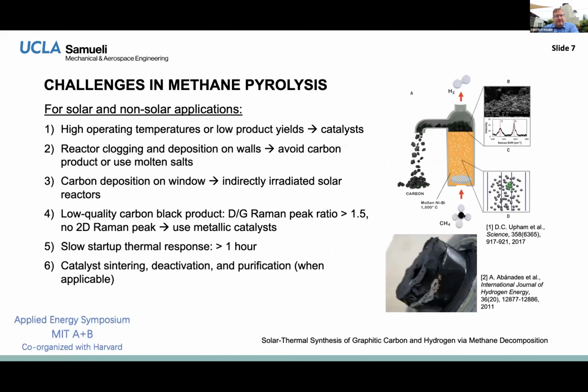There are a lot of challenges in direct methane pyrolysis. I won't read the slide to you, but you saw before that you have to operate at reasonably high temperatures. The reaction then goes pretty quickly, in many cases too quickly, right? So clogging and wall deposition, window deposition, all of these are big factors that have made direct solar methane pyrolysis difficult in the past. We have some ways of dealing with that, but even for us, sometimes it can be